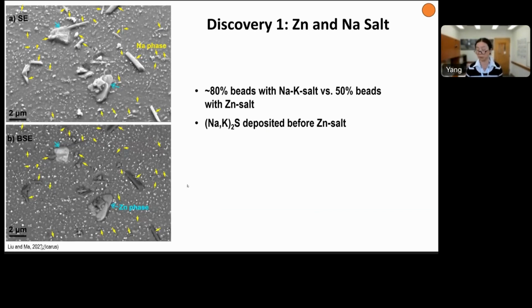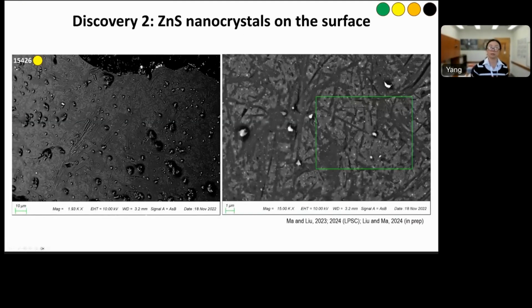We looked at the 45 beads. About 80% of the beads contain this sodium potassium salt, while only 50% contain zinc salt. So this is one discovery for orange bead, the first discovery. And last year at LPSC, my colleague Chu presented our discovery of zinc sulfide nanocrystals on the surface.